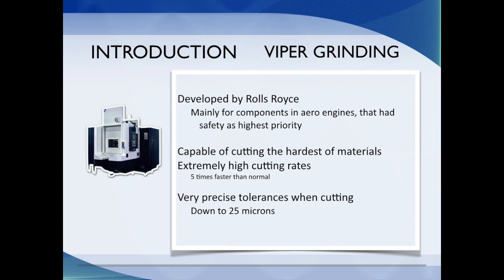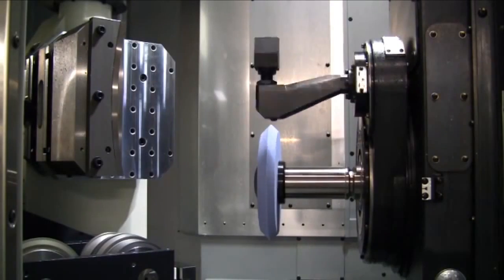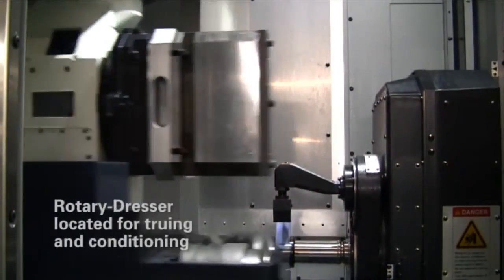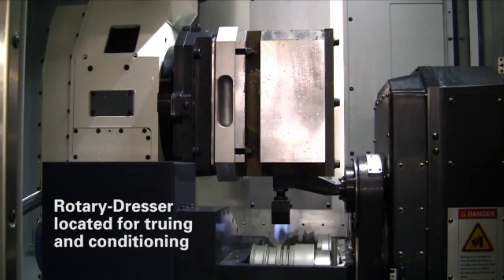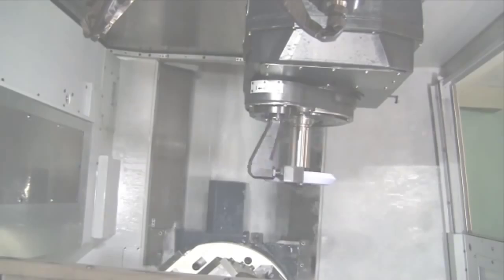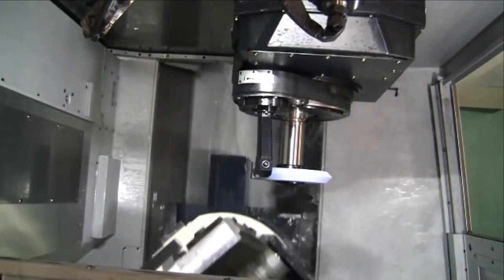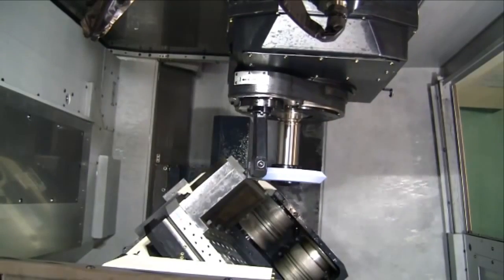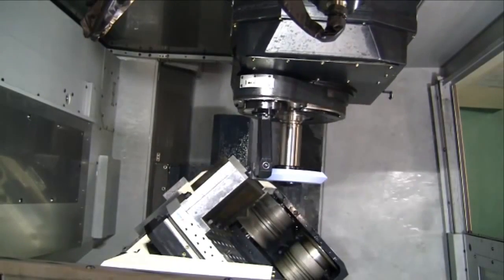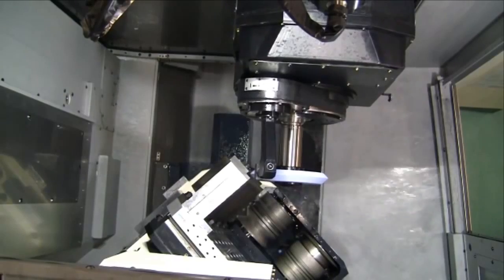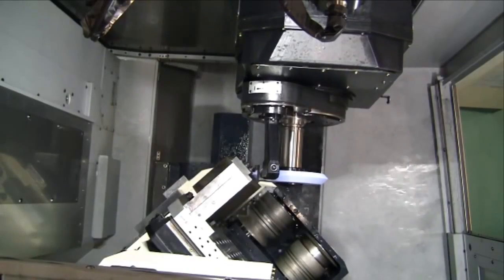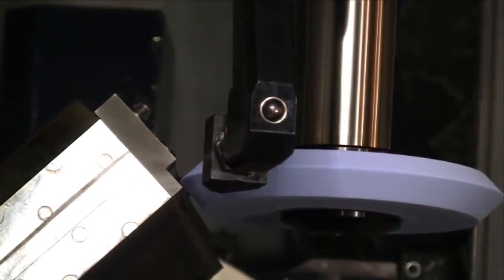Continuous dressing maintains constant pressure between the dressing roll and the grinding wheel, which is adjustable to ensure the proper amount of wheel is exposed during each revolution. This process is called microprofiling, as only a micron or less of the wheel is removed with each revolution. This ensures that the fresh, sharp, abrasive crystal is always properly supported in the bonding material of the wheel.